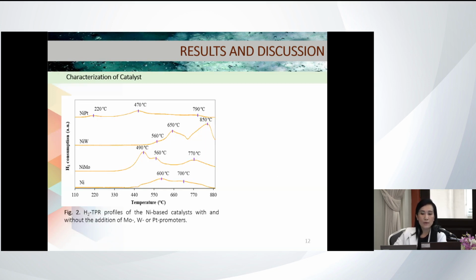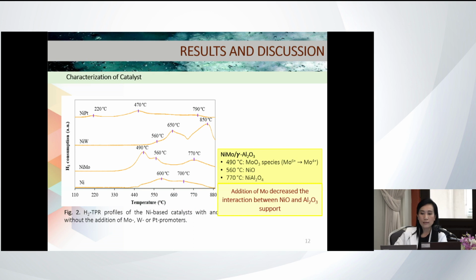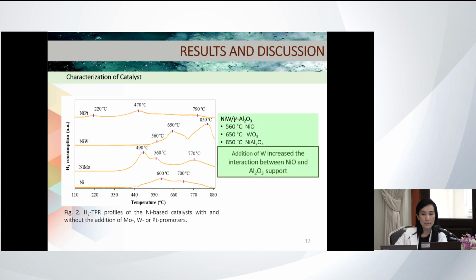This figure shows the hydrogen TPR profile to see the reducibility of the catalyst, and it shows that for the nickel catalyst, the reduction temperature is about 600 to 700. But after we add the molybdenum promoter, the reduction temperature decreased, and it means that the molybdenum can enhance the dispersity of the nickel oxide, and it also decreases the interaction between the nickel oxide and the support. And the result is also opposite for the nickel tungsten, because you can see the reduction temperature of this catalyst shifts toward the higher temperature. It means that the tungsten can increase the interaction between the metal and the support.